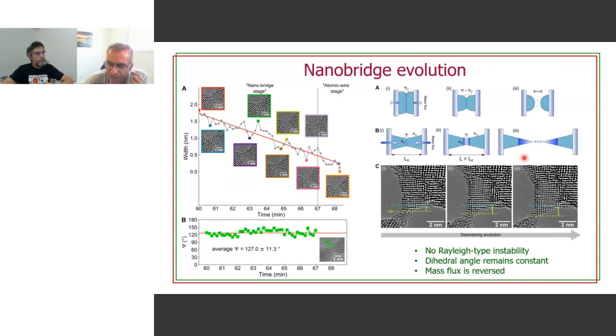So this was very strange to our experimental friends. And when we discussed that idea with them, they actually did not believe it too much. But they can basically go back to the microscope and see what's going on. We can actually determine if atoms are moving to the bridge or from the bridge as the sintering process happens. And this is the result. Actually, the theory is right, as usual, right? So atoms are actually moving through the bridge. You can mark a very well-defined atomic plane in blue here, and one in yellow, and you can follow how many atomic planes there are.